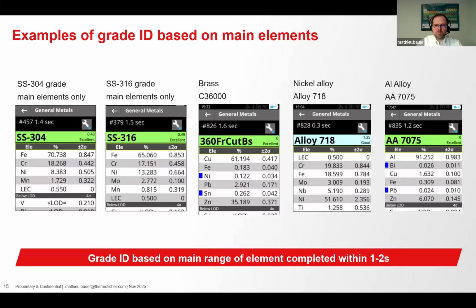Here are some examples of the main strengths of handheld XRF, with the ability to measure very quickly all the elements from titanium to bismuth and identify various alloy grades within a couple of seconds. That's, for example, the first two cases, which are grades of stainless steel, 304 and 316, which differ in their nickel and molybdenum content that can be very quickly measured using the technology. Also, brass or nickel alloys can be very quickly identified, and even some aluminum alloys can be identified within a couple of seconds based on heavy elements like, for example, copper and zinc for the 7075 grade. So overall, yes, the grade ID based on heavy metals can be completed within 1 to 2 seconds.